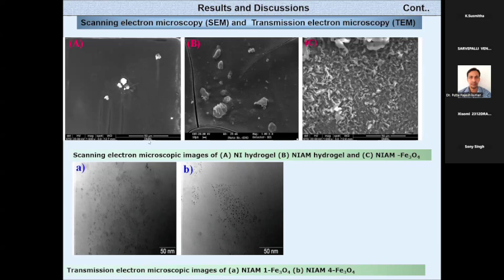Actually, this is a SEM image for this one, the iron ion loaded hydrogel network. Since it is in salt form, you are seeing some salty nature on this. It is not converted into nanoparticles, but when you are converting it into the hydrogel nanocomposite, you can see some small pore sizes, where your nanoparticles are entrapped into the hydrogel network.